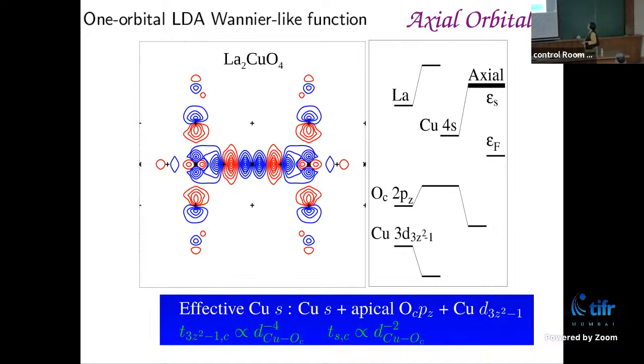I will not get into the details. The energy of this axial orbital basically determines your range parameter R. The higher this energy, the smaller the value of this R parameter. So this distance is controlling the energy of this axial orbital, and this axial orbital is determining the range of this wave function in plane. The more two-dimensional your wave function is, the higher is this range parameter, and the higher is this copper to apical oxygen distance.